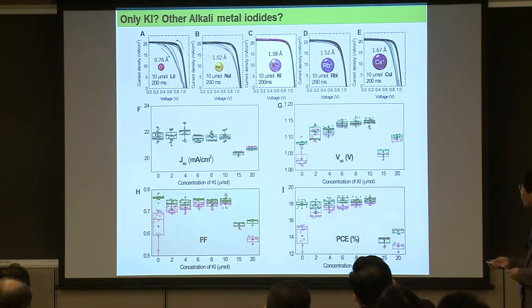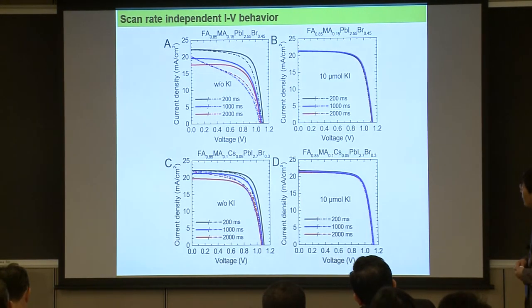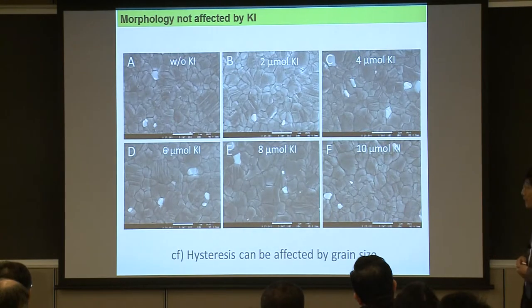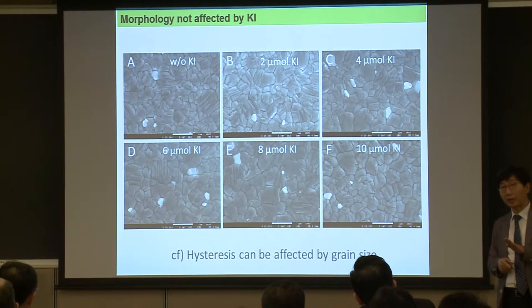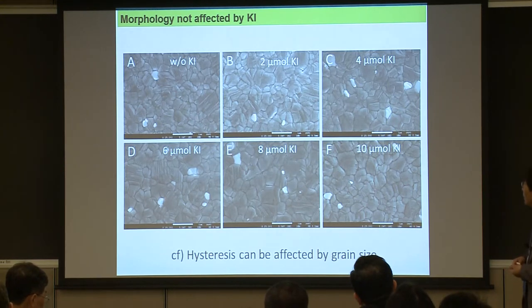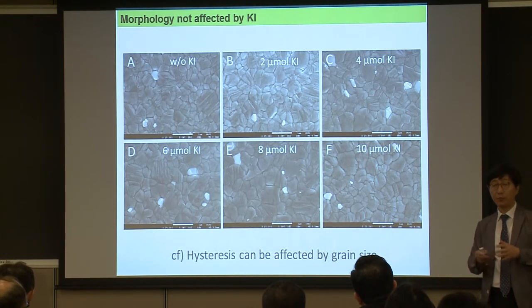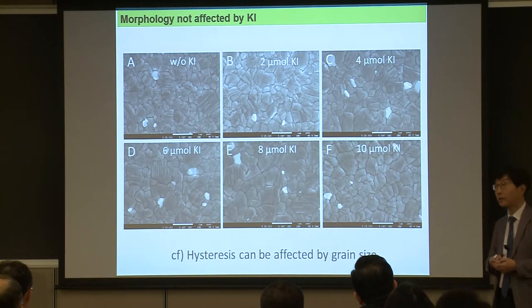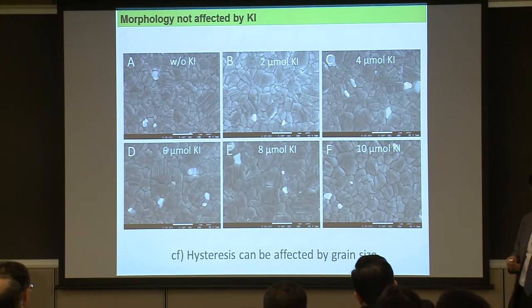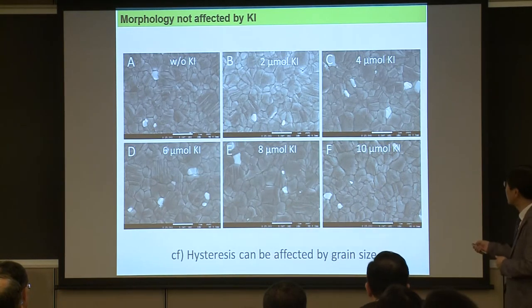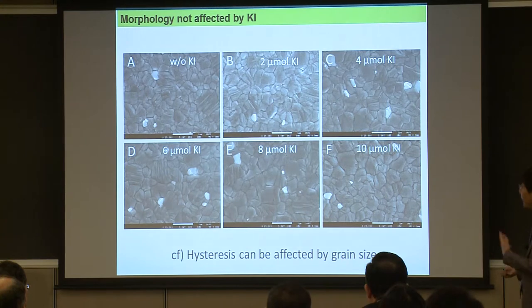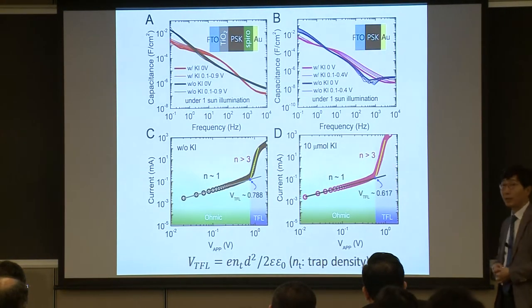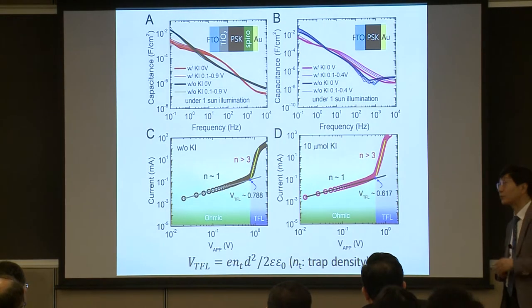create IV hysteresis. So also we found scan rate independent IV properties from this potassium iodide. And with the small amount of potassium iodide, in a micromole scale, we did not see any change of the morphology, because morphology change can also affect the IV hysteresis. If you increase the grain size, you probably reduce the IV hysteresis. So to see whether it is the potassium iodide effect or the morphology effect, we investigated morphology change, but there is no change of the morphology after adding a small amount of potassium iodide. So this removal of IV hysteresis is related to potassium iodide.